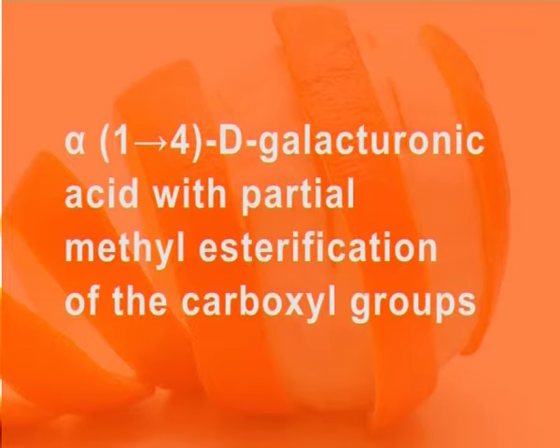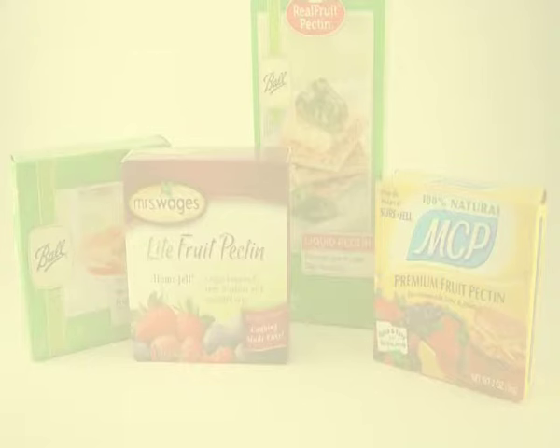Commercial pectins are structurally less complex due to industrial extraction and purification processes, which remove most of the neutral sugars. This consists mainly of a backbone of alpha-1,4-D-galacturonic acid with partial methyl esterification of the carboxyl groups. At least 65% of the extracted material must be galacturonic acid in order for the extracted material to be classified as commercial pectin.